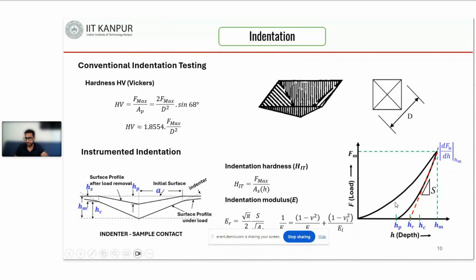So what is the benefit of it? With the load-indentation curve and some set of formulas, we can get the hardness and the modulus values. Since the indenter has a known geometry, like a pyramidal indenter, we know the area of the indenter as a function of indentation depth. So we can measure the maximum depth at the maximum load, calculate the contact area of the indenter with the sample, and since we know the maximum force, we can calculate the hardness value.